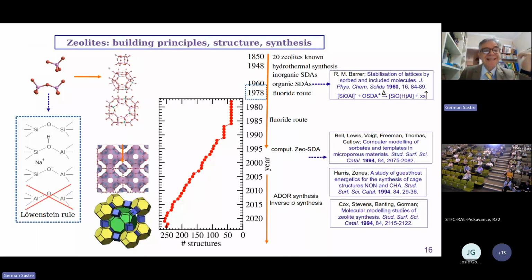On the left, you can see tetrahedra of silicon or aluminum, and oxygens in red, sharing corners, then the dimers, and then they polymerize, the silica and alumina polymerization reaction, and then the oxygen bridge, and you can see several examples. Particularly when aluminium enters into this compound, this formally negative charge can be compensated by cations such as sodium, but when the cation is hydrogen, it is covalently bonded to the bridging oxygen, making a Bronsted site, which is crucial for catalysis.